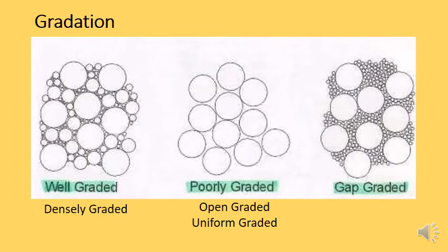Now, there's an issue with size that we need to take into account here. One thing I do need to say about size is that it can influence the strength of the aggregate. Remember, the aggregate will be stronger in compression and tensile and all directions, but compression really is what we're talking about here. The lower the void content is, the lower the void ratio. So obviously, if you have an aggregate where the particles are all the same size, the smaller the particle size, it will have less void content, and so generally it will be stronger.